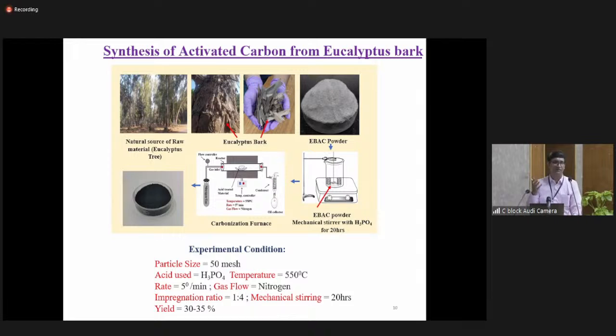500 to 800 degrees centigrade, in which we have to see what the surface area is as well as how much percentage of conversion from biomass to activated carbon takes place. So this we have optimized to 550. The rate to reach 550 degrees centigrade is 5 degrees centigrade per minute. The rate is also a very important point when you are making activated carbon: how fast the heating is going on, or how slow it is. The surface area also depends upon this rate of heating.